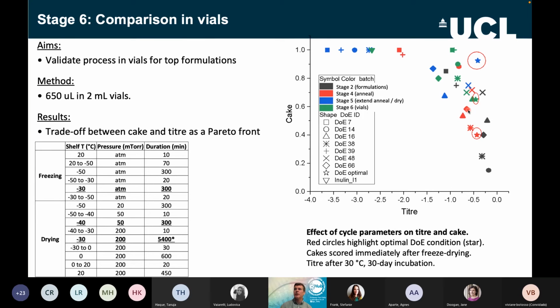I just want to show on here particularly the optimal formulation, which is circled in red. They're the stars. So you can see the titer is robust. The optimal formulation, regardless of the process, gives different cake scores but keeps the same titer. And so actually the vial sat somewhere here at a score of about 0.7, which is good enough, I would say, in terms of cake performance.